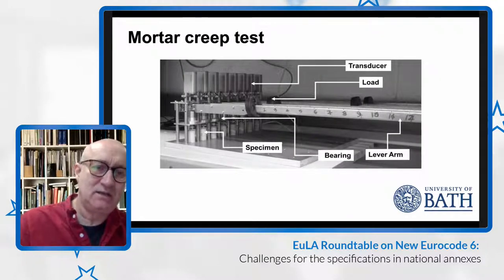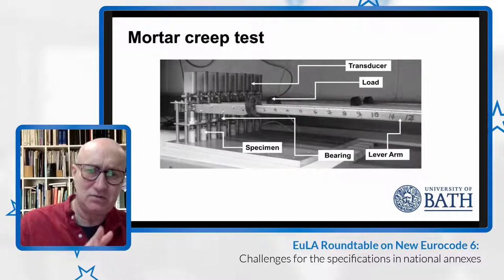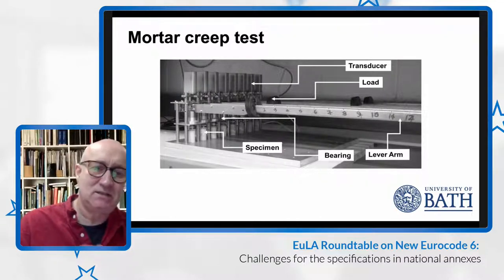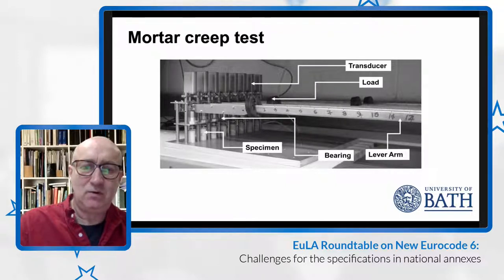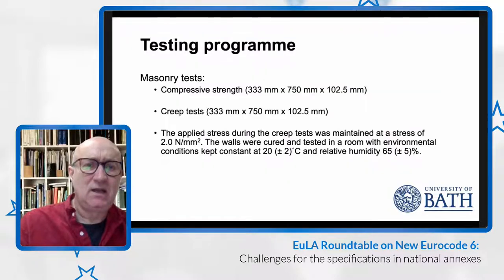Now, I appreciate that in terms of static load testing, if you developed a static stress-strain relation curve and based it just on the platen movement, because of the end effects and the effects of the platens, the strain levels you would measure would be higher than if you measured surface strains, as we saw from what Meera had done, for example, in measuring her strain values.